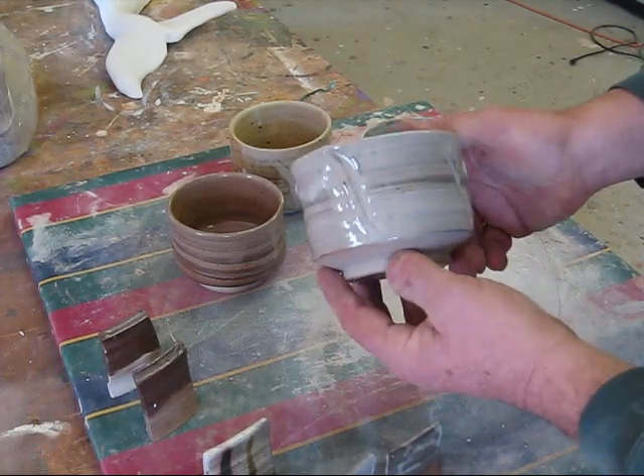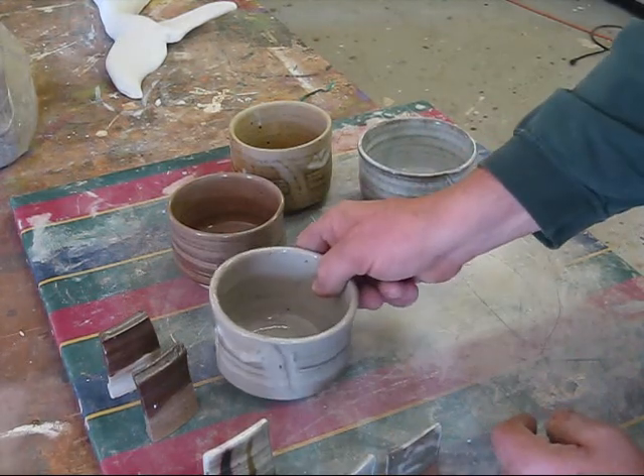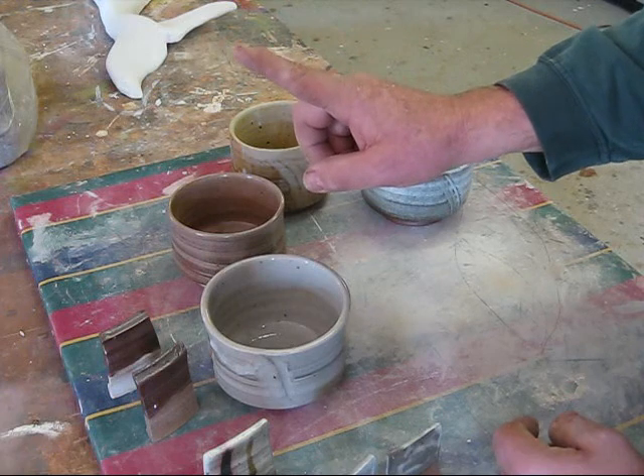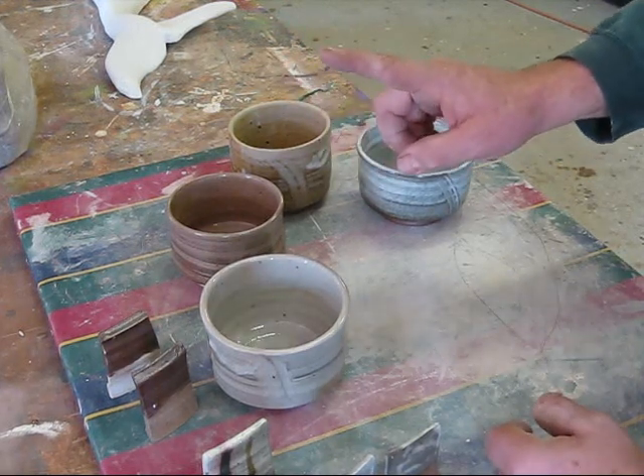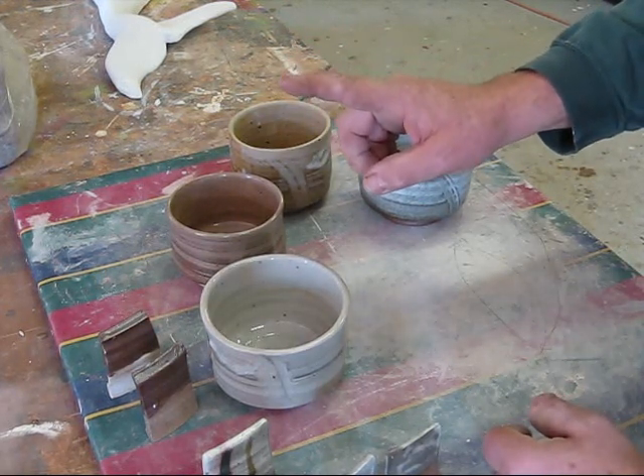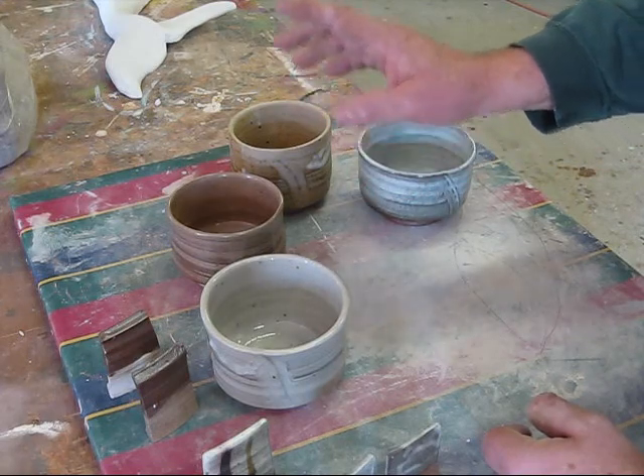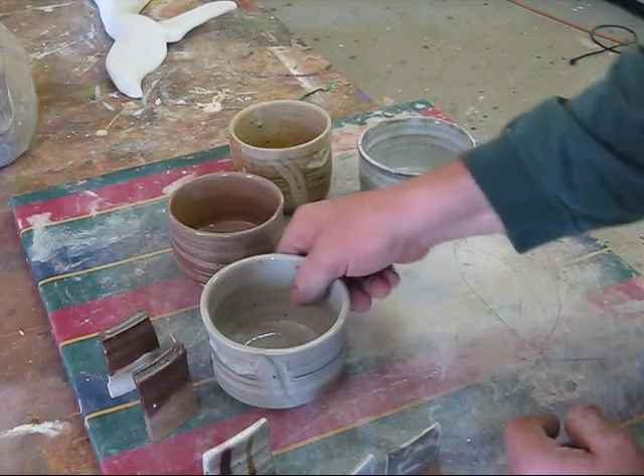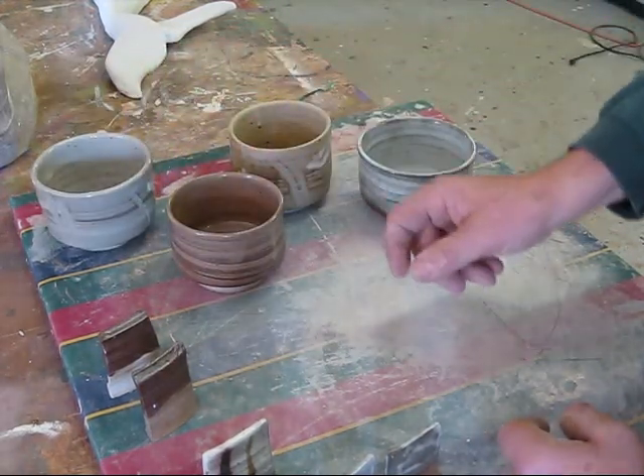These were electric fired to cone 10. Cone 9 laid over a little bit, and cone 10 was still straight up. But my pyrometer said I was up to 2361°F, so I was up temperature-wise on my pyrometer, but the cones weren't agreeing.